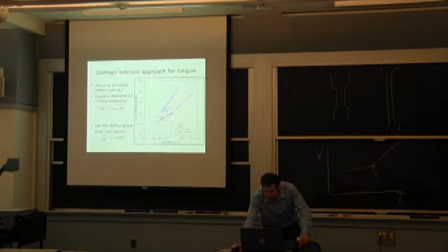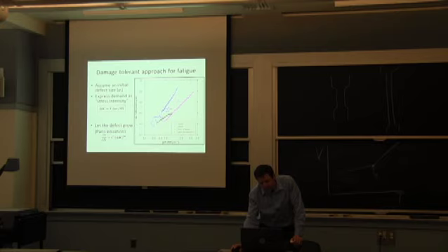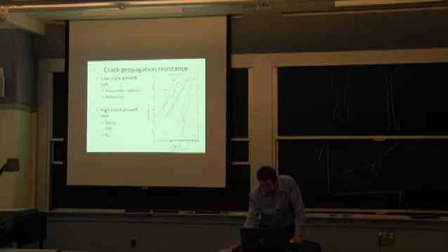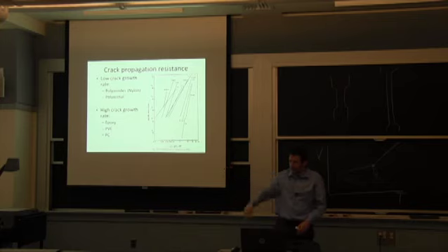We can skip that. You can use the same type of approach with the plastics that we talked about for the metal in terms of fatigue. You can have a crack propagation analysis that's based on linear fracture mechanics. We have the Paris equation that's giving us a constant rate between the log of stress intensity and the crack propagation rate. These are some of my experiments. Here you can see in fatigue, the epoxy is really terrible because it doesn't form that plastic zone that we talked about. So it's just going to crack right through.